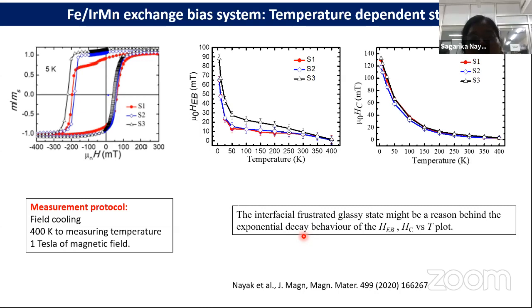To study the interface, we perform various magnetic measurements. One of them is this temperature dependent study. To perform the temperature dependent study, we first field cool the sample from 400 Kelvin to the measuring temperature in presence of 1 Tesla magnetic field, and we took the hysteresis loop and calculated the value of exchange bias field and coercive field and plotted against temperature.